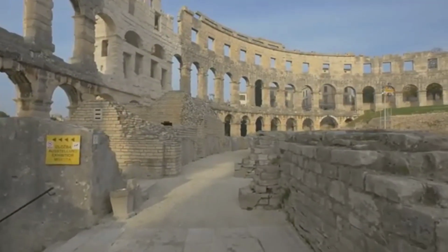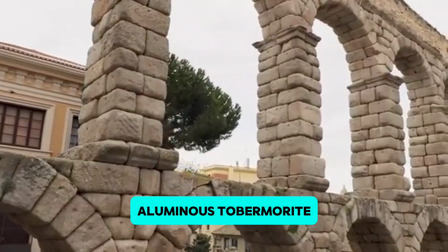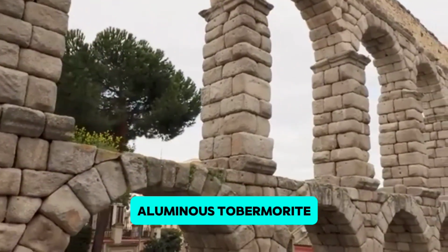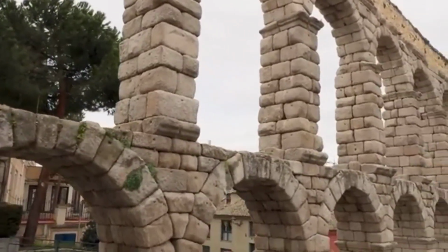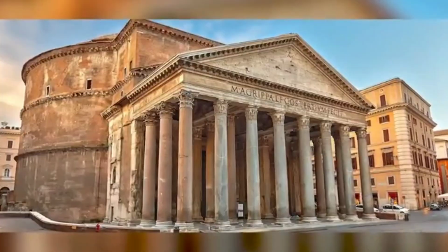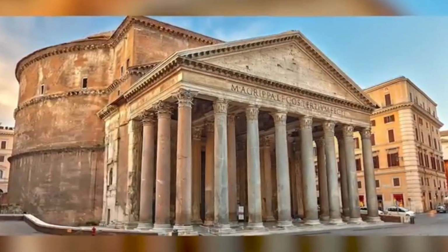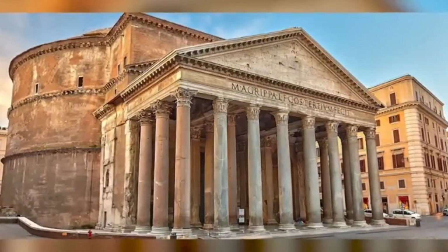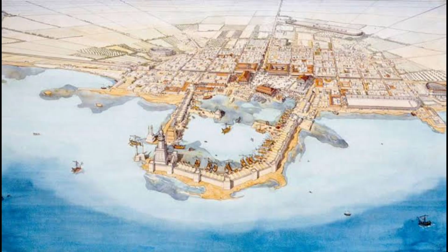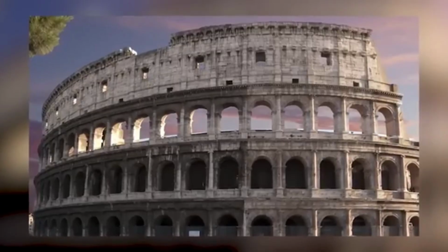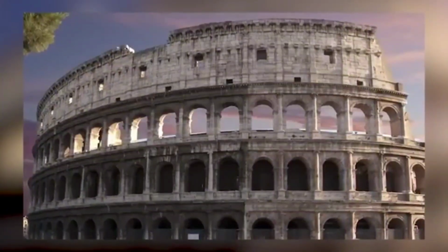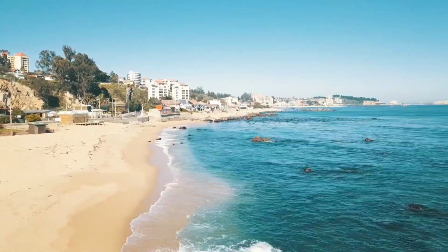The primary cementing mineral that formed was something called aluminous tobermorite, a layered mineral that grows as fine fibres and interlocking plates, reinforcing the concrete from the inside like a microscopic scaffold. And in Roman maritime structures, harbour piers, breakwaters, the great port of Sebastos, something even more remarkable happened. When seawater percolated through the concrete, it didn't destroy it, it made it stronger.